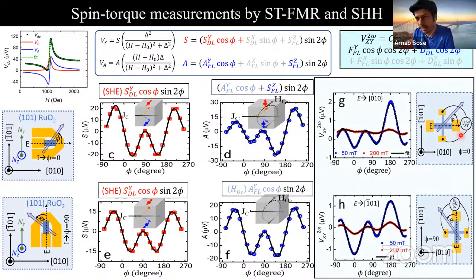Just to remind you, in this case, we apply low frequency current in the system and measure the Hall voltage by rotating an in plane magnetic field. And we record the second harmonic Hall voltage as a function of phi. Again, we can clearly see the distinct difference in the angular dependence in these two cases.